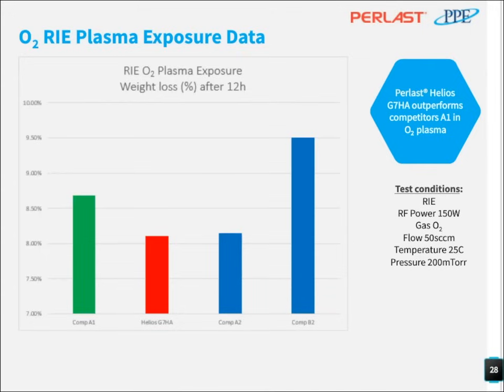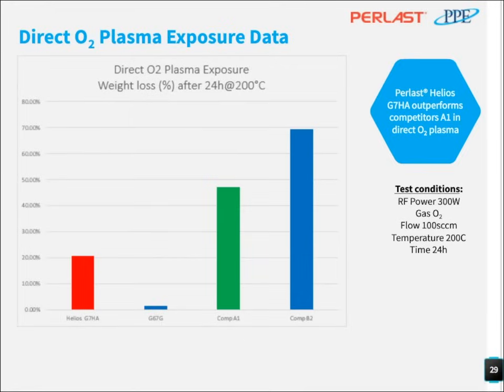the inorganically filled competitor material. Okay, finally, we have direct oxygen plasma data. This test was done in a CCP tool, which is a parallel plate capacitively coupled plasma. The formulations our scientists developed are, again, significantly better than competition under ion bombardment. This kind of plasma generates quite a lot of ion bombardment. Anyway, to sum up, Perlast Helios G7HA material has excellent plasma performance in lots of different chemistries. It offers excellent high temperature sealing performance and really high purity.